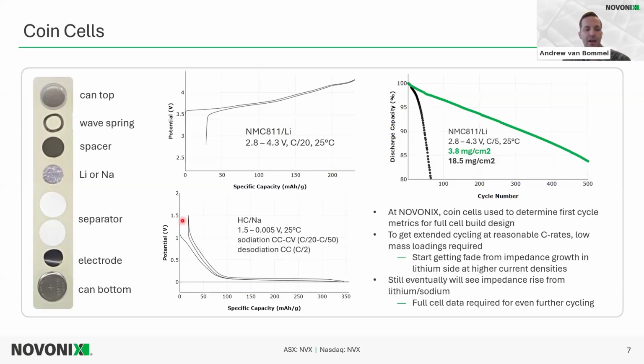Here's another coin cell, some more data on hard carbon in a sodium coin cell. In this case, the hard carbon is sodiated from OCV, which looks maybe around 1.5 volts, down to 5 millivolts. And then there's a CV step until C/50, and then desodiation at C/20 again, up to 1.5 volts.